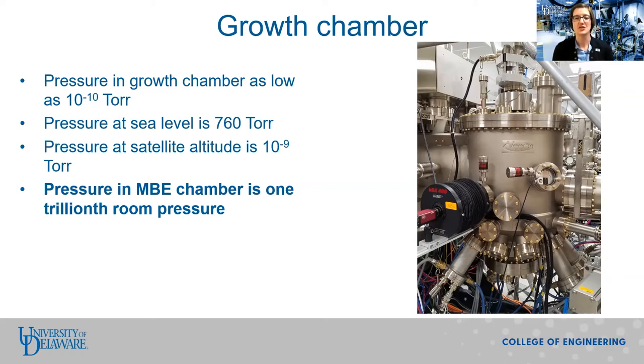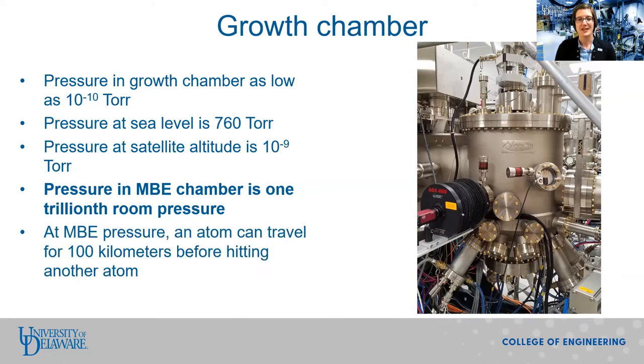This is extremely important because we're depositing our films one layer of atoms at a time. If we had any air in the growth chamber, the oxygen or water vapor molecules might incorporate into our film, and this would ruin the crystal. At the pressure in the MBE, an atom can actually travel over 100 kilometers before it would hit another atom. So we work very hard to keep a low pressure in the growth chamber so that our films are as atomically perfect as possible.